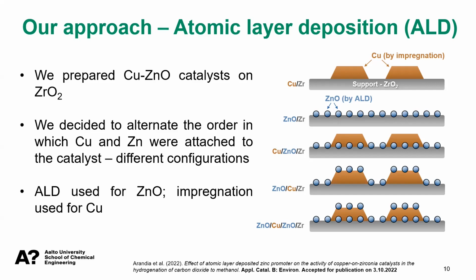For the first one, we have the support and we put the copper by impregnation, and ideally we have something like this. In this case, we apply the atomic layer deposition and you see we have something like lonely zinc oxide species on the zirconia support. Then we also prepared a combination of both. In this case, we put the copper on zinc oxide zirconia. So basically we had this and we put the copper on top of it, or after the zinc oxide. And this is the inverse, so zinc oxide after copper on zirconia. And finally, we also tried zinc oxide, copper, zinc oxide, zirconia. So you see that we prepared different configurations in order to study their activity.